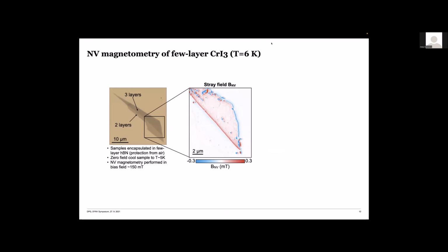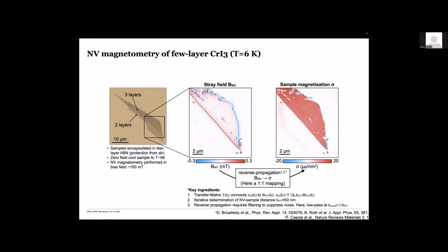Okay, good. So what I was saying, I'm not sure if this was muted already, is that one can reverse propagate these data. And in the case here of a uniaxial out-of-plane magnetized sample, this is in fact a unique mapping that allows us to recover the underlying magnetization pattern in this material. And again, it just confirms what I said before, 0 magnetization on the bilayer and a magnetization of about 15 spins per nanometer square on the trilayer. And by the way, this number matches very nicely with what was expected with this material to begin with.